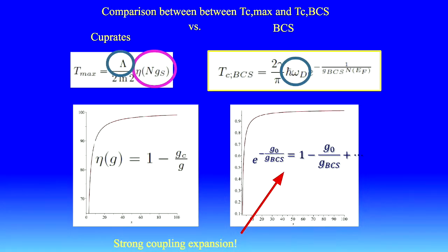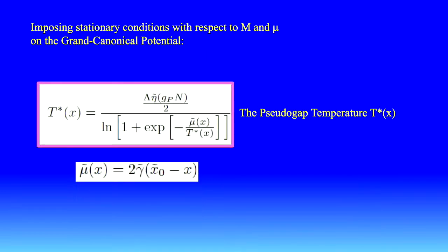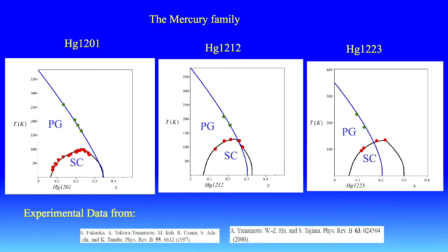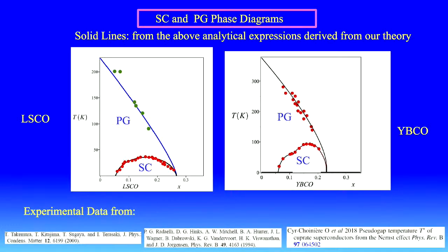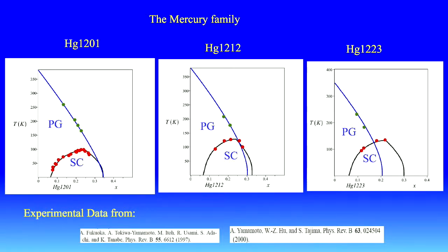So if we plot this, adjusting just the gamma, you see, this is for LSCO, this is for YBCO, this is the superconducting dome, and this is the pseudo gap. These lines are obtained from the previous expressions for TC and T star. These are the experimental points. Here, the mercury family. So there's no theory so far that has even intended to describe this curve.